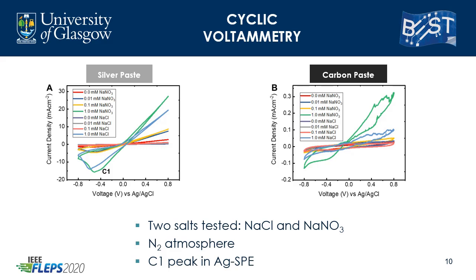with the solution. In Figure A, we can observe that the presence of salt seems to influence the silver electrode response current. The current density increased with the conductivity of the solution by increasing salt concentration, and it is more significant in the silver electrode than in the carbon electrode. Even at different concentrations of sodium nitrate and sodium chloride, carbon appears to stay mostly inert, while the silver electrode clearly shows similar cathodic peaks at around minus 0.5 volt for both salts.